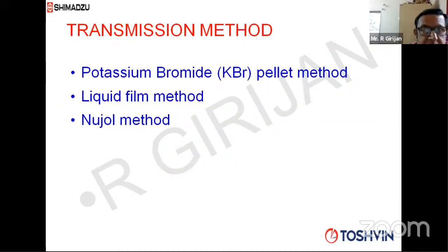Okay, transmission method, potassium bromide pelletization method. That is the one which was used for a very long time. Nujol method can be used for sticky material, or the liquid film method, where you can dissolve the powder material, solid material, in a suitable solvent, make a solution, and keep it on a pellet. Pellet means a crystal, like potassium bromide crystal or sodium chloride. So many crystals available, and keep it under an IR lamp.